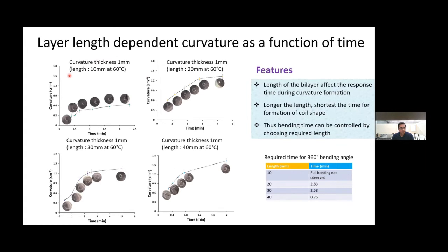We also observed the layer length dependent curvature formation, and we have found that the longer the length, the shorter the time for formation of the coil shape. For 20 millimeter length at 60 degrees Celsius, it takes 2.83 minutes, and for 40 millimeter at 60 degrees Celsius, it takes only 0.75 minutes.